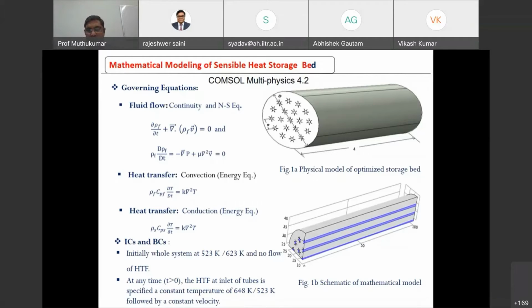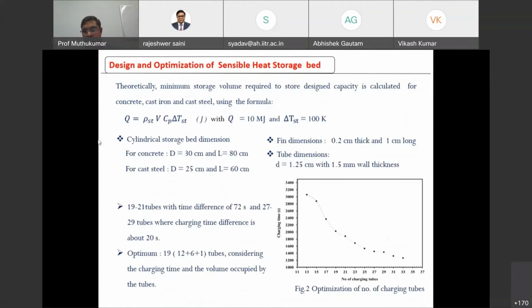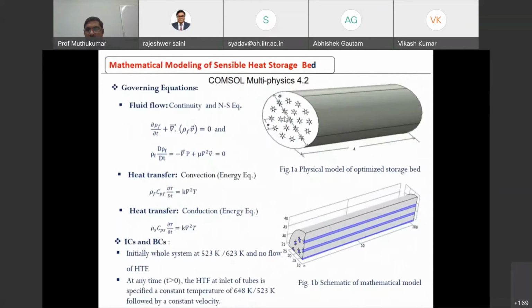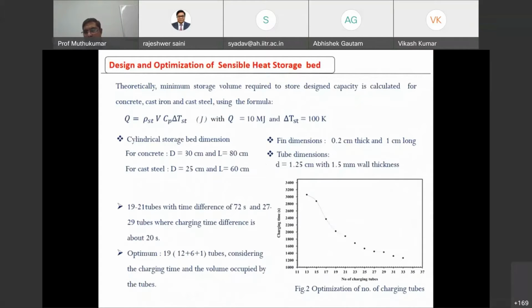The initial and boundary conditions can be set based on the charging and discharging process. The input values can be the fluid velocity and the temperature of the fluid. All these things can be specified, and then you can solve the system. Here we varied the number of charging tubes, keeping the symmetry of the system. Symmetry means if you take a diagonal line, both sides should have an equal number of tubes. By keeping the symmetry, we varied the number of tubes, and accordingly we predicted the charging time.